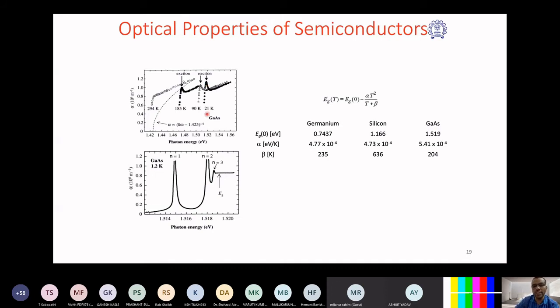That is very fine. What is the next observation? If you have good observation skills, you find that as you reduce the temperature, the slant of this excitonic edge is also getting reduced. So you get a steeper absorption rather than a slanted absorption. Your Urbach energy is also being reduced, and your exciton emission peak is becoming much more dominant as you reduce the temperature.